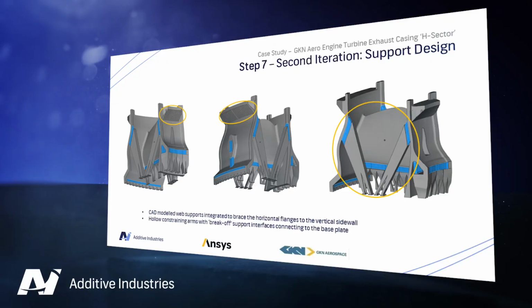So, based on that, we decided to tackle some of these key problem areas where the magnitude of distortion was really quite high with an updated support design. So what we decided to do was remodel some solid CAD supports to the large flange areas where we were seeing a large change in cross-section, and also add some hollow constraining arms with a break-off interface attachment connecting down to the base plate to give a little bit more stiffness and rigidity to those vertical flange features.